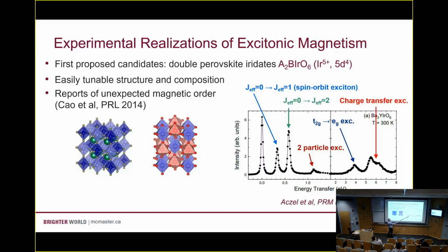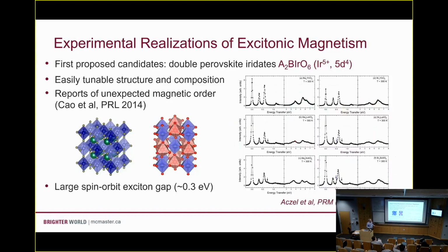And what you can see here is in these double perovskite iridates, this energy gap is very big. It's about 300 millielectron volts. Way too big to close just as a function of temperature or with most normal perturbations. So this excitonic magnetism picture really doesn't seem like it has much to do with these materials. The gap is just way too high to close for normal circumstances.